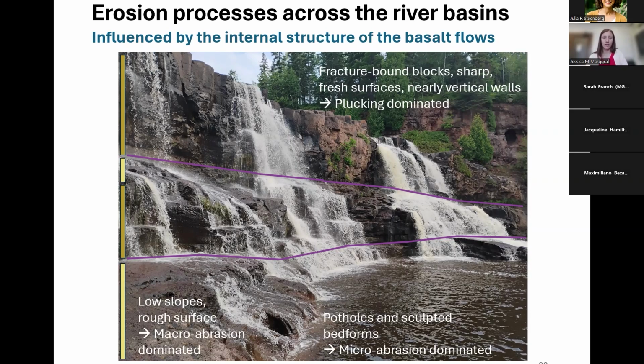And they look more like fresh surfaces. And in this area, they also tilt a little bit downstream, related to the dip of the basalt columns, the basalt flows in total. And here we can really see that these areas are much more dominated by plucking, related to this observation, which are more in the bottom of the basalt flow. We can see it a bit similarly down here, again with this kind of structure.